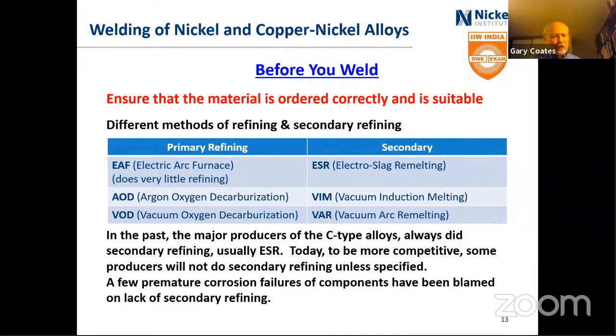But a number of producers around the world have said, well, that's an expensive operation. The ASTM spec doesn't require it. So to be more competitive, they skipped the secondary refining method. Since that time, and that was probably 25, 30 years ago that started, there have been a number of corrosion failures of components that have been blamed on the lack of secondary refining. Now, in 90% of the cases, there haven't been a problem, but in maybe 10% there is.